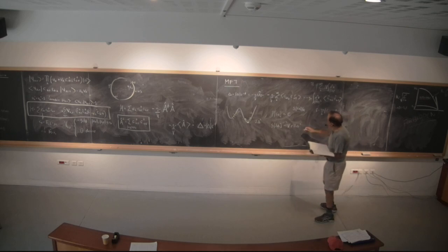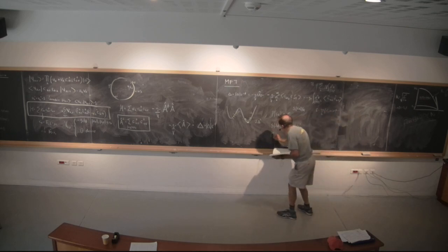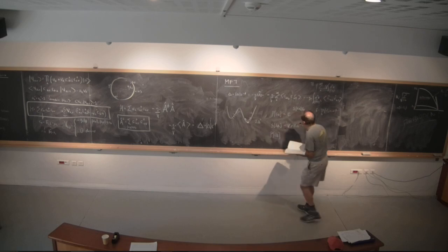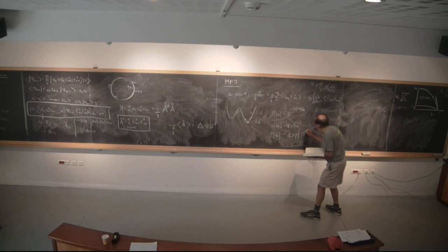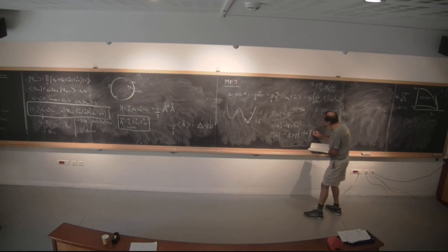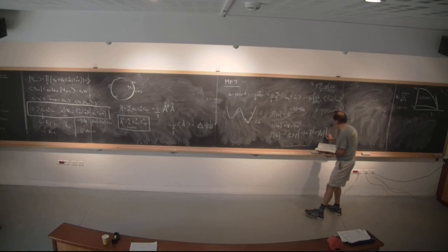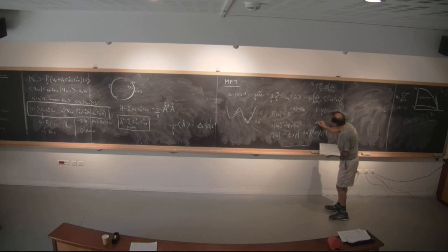Therefore, if I look at this distribution function, which is really something inside a path integral, but let's not worry about that right now, it has an exponential of minus delta lambda squared divided by h bar times R inverse divided by V. In other words, the order of magnitude of delta lambda squared is proportional to h bar over R V.